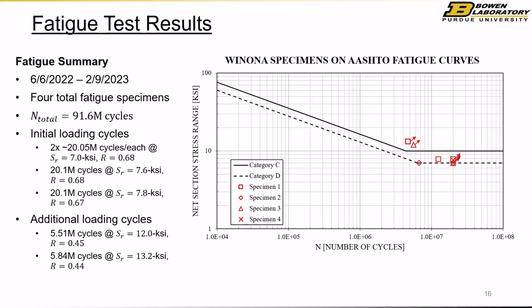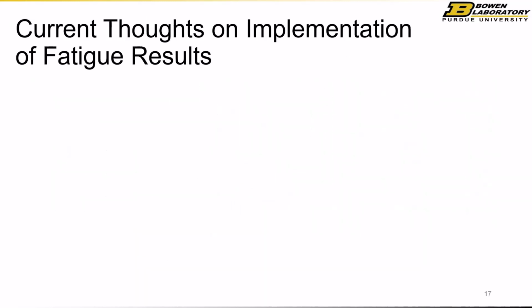Well, if the distortion gives you a stress concentration, right? If that distortion doesn't exceed the stress concentration associated with a plate with a hole in it, basically a stress concentration of 3, then you're not going to see worse behavior. Does that kind of make sense, right? The distortion amplifies the local stresses. You get bending, you get this stuff going on. But if you don't exceed anything worse than what the hole is, just from the pack out, then it kind of makes sense that you wouldn't see a reduction in fatigue strength.